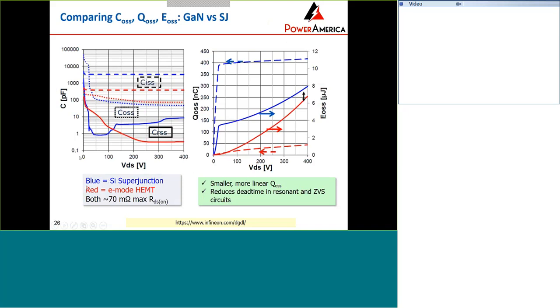The gallium nitride devices exhibit lower capacitance values. It has lower input capacitance and Coss, and the CGD or Crss shows a pretty linear behavior compared to superjunction. If you compare the total charge in the Coss and the energy stored in the Coss, the gallium nitride, shown in red here, has lower values than the superjunction. So it indicates that gallium nitride devices could operate at an even higher frequency than the silicon counterpart, because the dead time could be reduced in some applications.